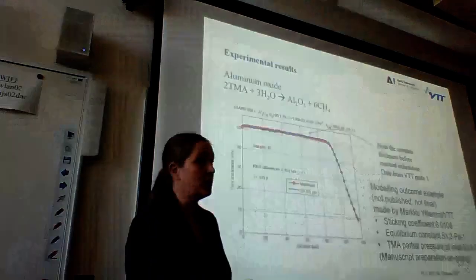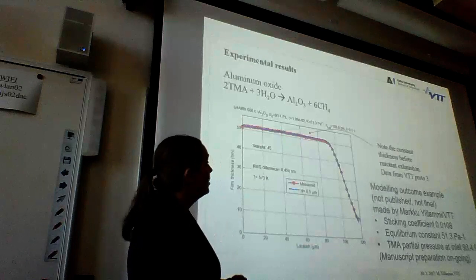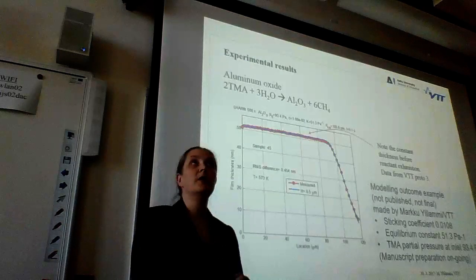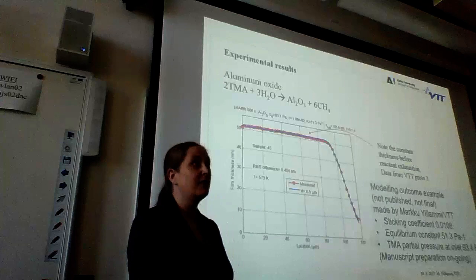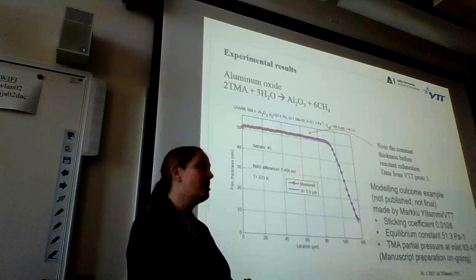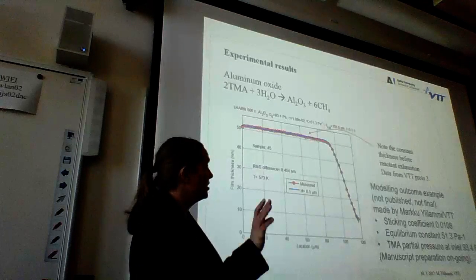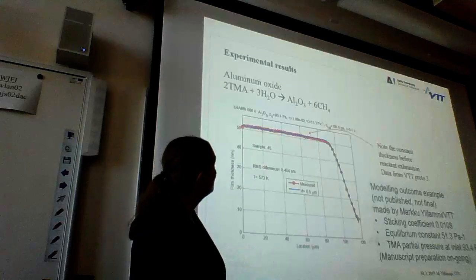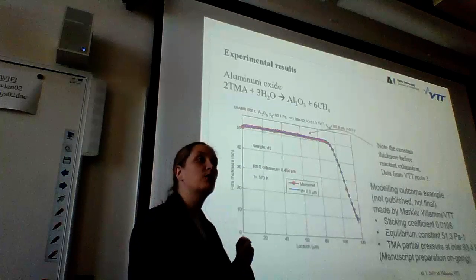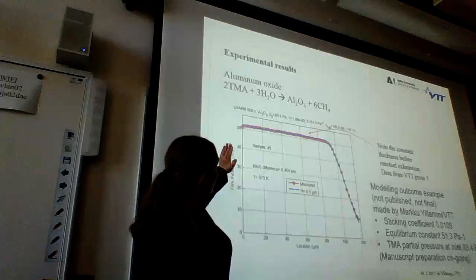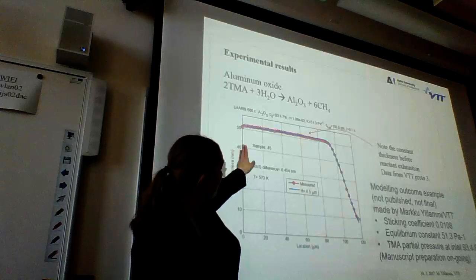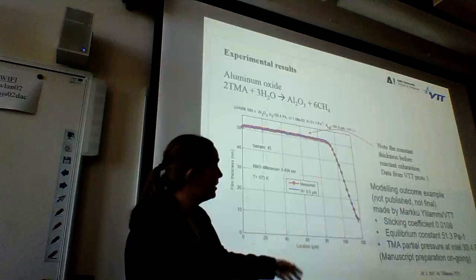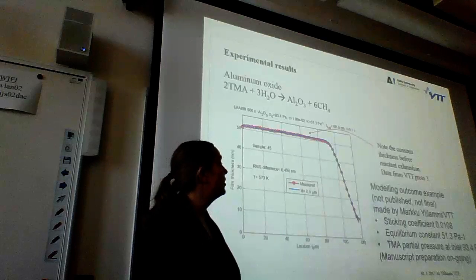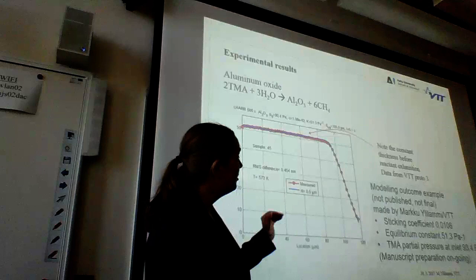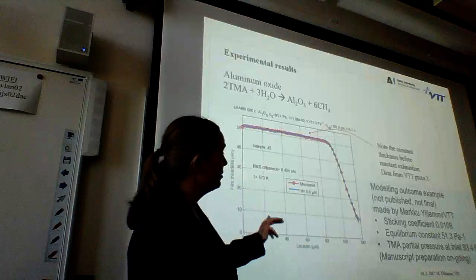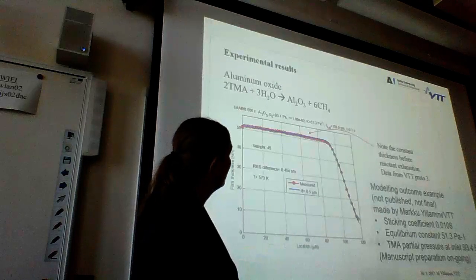And we are also doing some modeling ourselves. I have a colleague, Markku Ylilammi, who made his thesis on ALD in '79, so pretty experienced in ALD, but he has actually been doing other things. He's an expert on modeling, and he grabbed the chance of doing modeling for ALD. This is one of our graphs for the TMA water process, and he has extracted a sticking coefficient of 0.0108 and an equilibrium constant for the reaction, and also calculated the TMA partial pressure at the inlet.